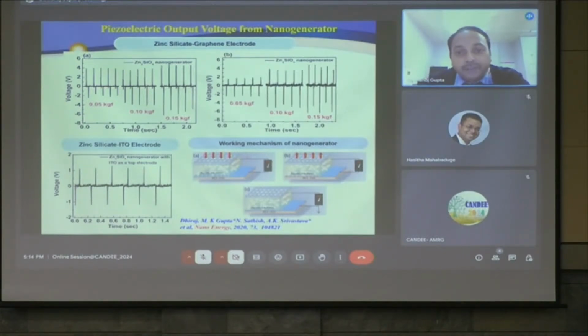And this is a reverse test of the nanogenerator, just to ensure this. See here, the signal is in the positive direction, and here the signal is in the reverse direction. It means if you change the connection, positive to negative and negative to positive, you can reverse the piezoelectric signal, just to ensure that it is from the piezoelectric phenomenon, not from any other source.